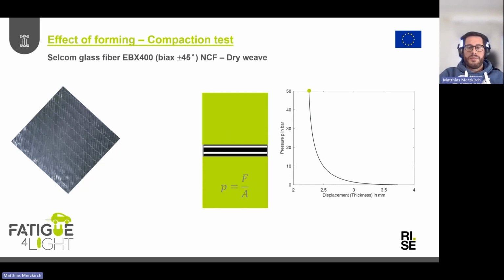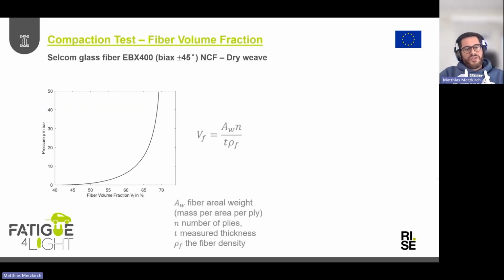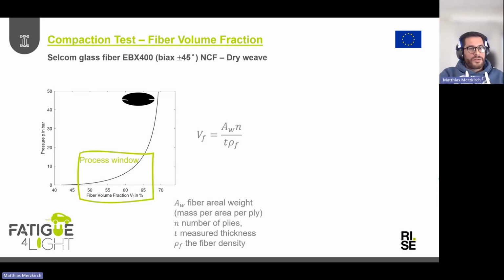How is that helpful? It is to find the transition to the volume fraction. The volume fraction can be determined by knowledge of the amount of layers that you're using, the fiber density, the measured thickness from the test, and also the areal weight, so the mass per area per ply. In that case, you can calculate a volume fraction out of this force displacement relationship. And if you don't put any pressure at all, the fibers are very loose. So we want to compress them, put them a little bit more together. If it's too much, they will just break. A rough estimate for the process window is shown here, at relatively low pressures.